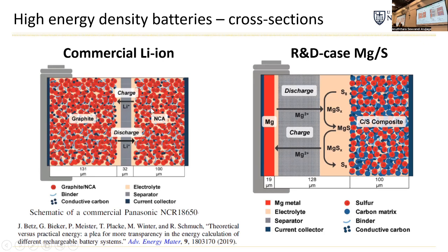And that's on each side of the cell. And then the electrolyte resides in the middle, but the electrolyte also has to fill in all the pores within the electrodes inside here. And this schematic shows an R&D type case for magnesium sulfur cells. Magnesium sulfur electrochemistry is very challenging.